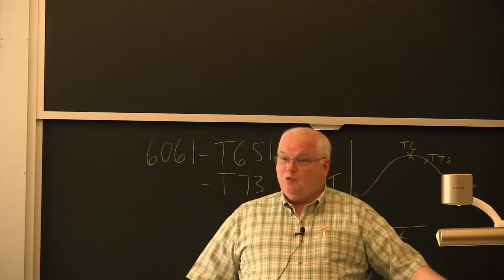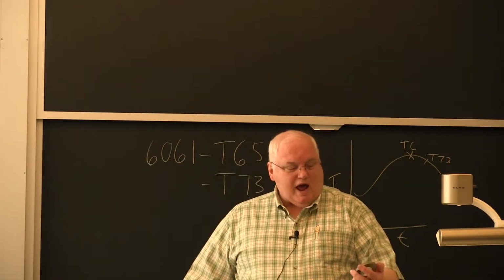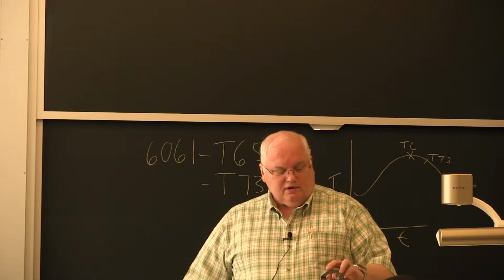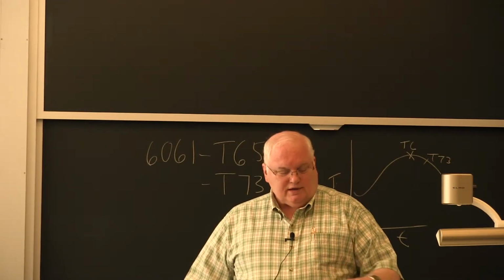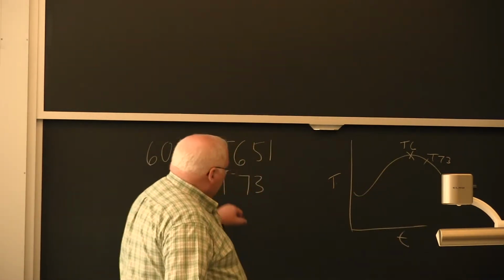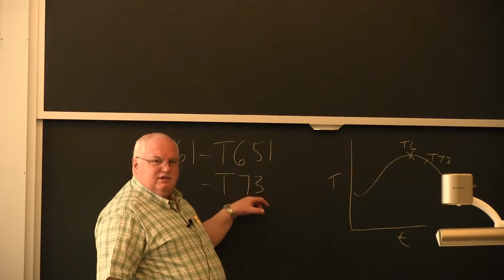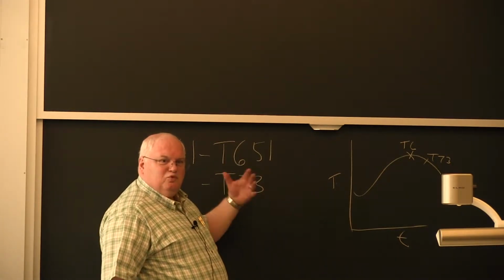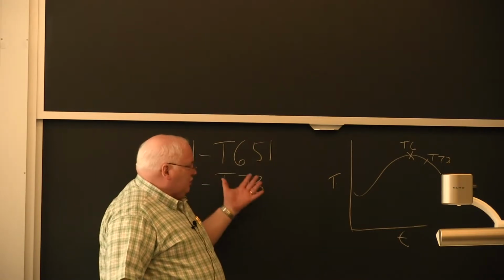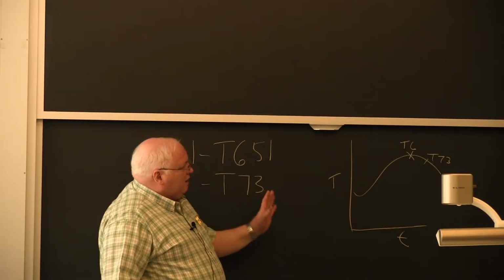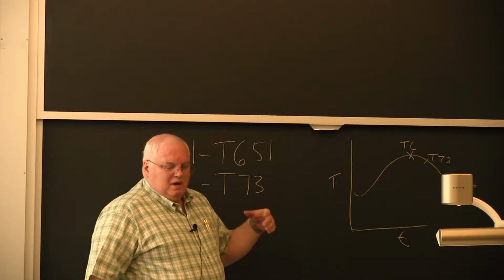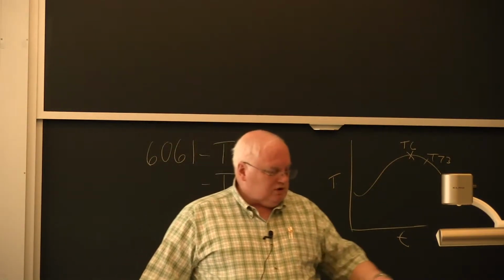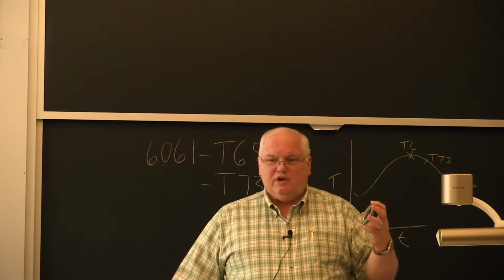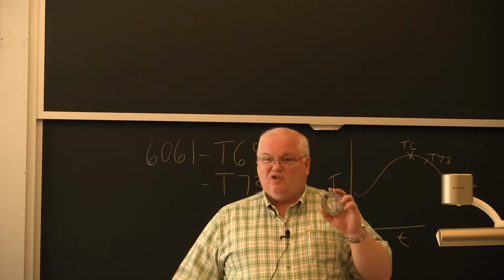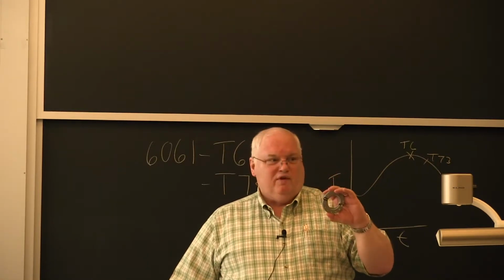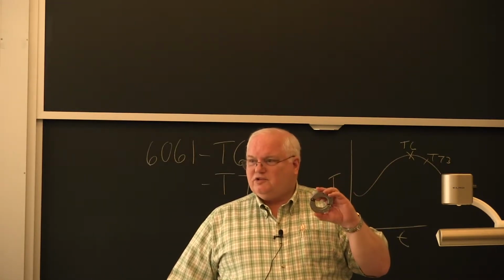Well, it turns out the washer is exactly the same. And what had happened is they investigated this failure that killed a few people in Arkansas, and they said, oh, this other helicopter group had seen this problem, and they had switched from T6 to T73 to get double the resistance to stress corrosion cracking in the aluminum alloy by going to the overaged condition. And so Sikorsky said, oh, well, we better order some new washers of T73 that won't stress corrosion crack, because they started looking and they found these things sitting on the shelf in Navy supply depots with stress corrosion cracks in them.